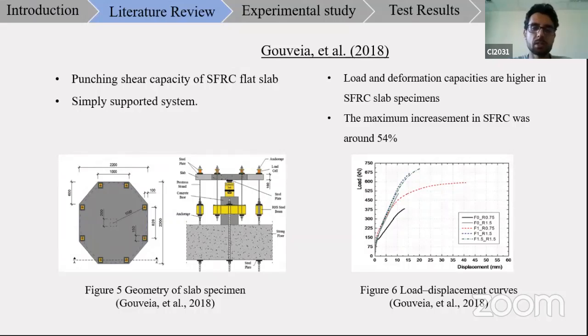The first one is Gouveia et al. In this study, punching shear capacity of steel fiber reinforced concrete flat slab is investigated. And the slab specimens were cast in octagonal form and tested in a simply supported system as shown here, and loaded by a hydraulic jack from the bottom and through a steel plate of 200 by 200 millimeters. And the load deflection curve is shown here.